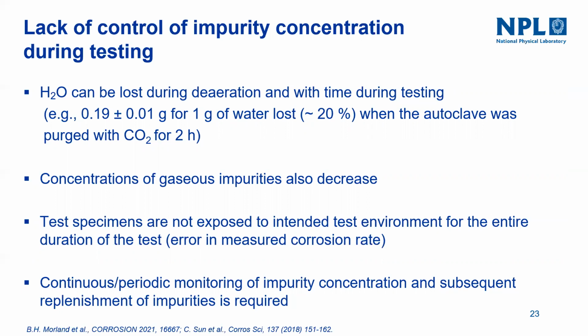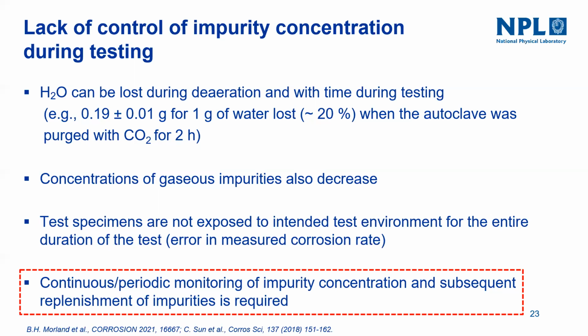The other one is the concentration of gas impurities. We all know that the gases dissolve in the condensed water. These can also dissolve in the liquid water. So whatever gas concentrations of impurities are put in the autoclave are normally lower than the intended values. Technically, the test specimens are not exposed to the intended test environment for the entire duration of the test. So the key is we need to have a continuous monitoring system. If there is a depletion, then either stop the test or replenish the test environment with the impurities.